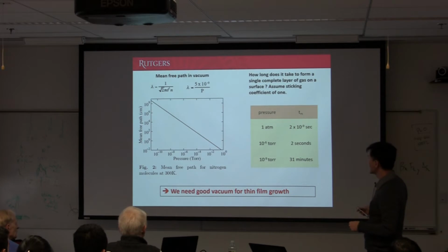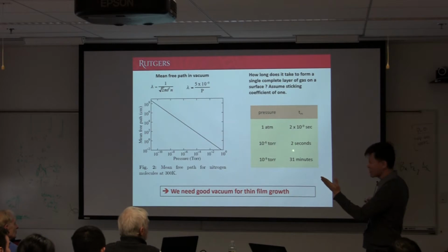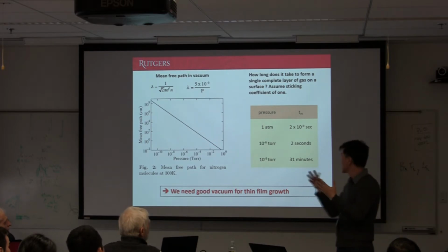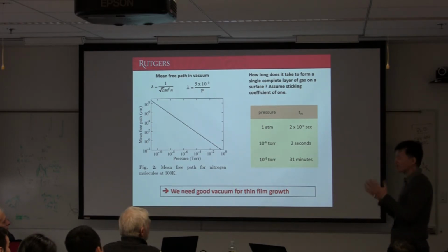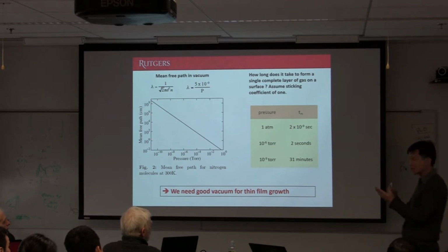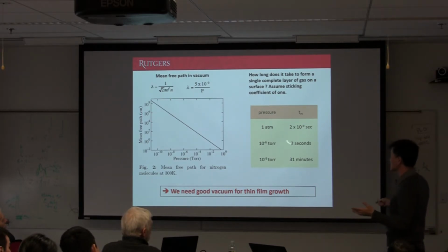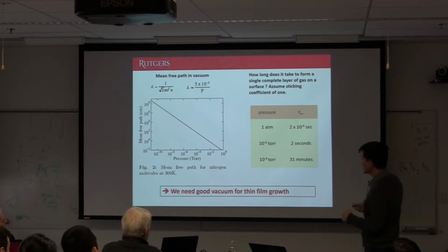The second thing, which is usually what limits you more, is this: if the vacuum is, let's say, 10 to the minus 6 torr, then your substrate is coated by air, and it takes roughly 1 second to coat your substrate, if air has a 100% sticking coefficient. Okay, air does not have a 100% sticking coefficient, so they don't grow, but at least you can see that the surface will be oxidized in a matter of just a second if it is reactive.